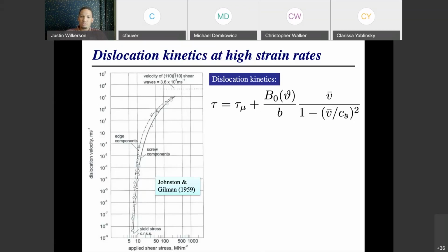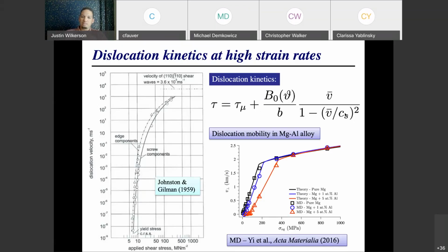And then these mobility relationships are actually really convenient to characterize through molecular dynamics calculations. So in this case, we characterize this drag coefficient, B0, as a function of temperature and as a function of the concentration of solute atoms in a magnesium aluminum alloy. And that's a pretty straightforward use of multi-scale modeling in that case.